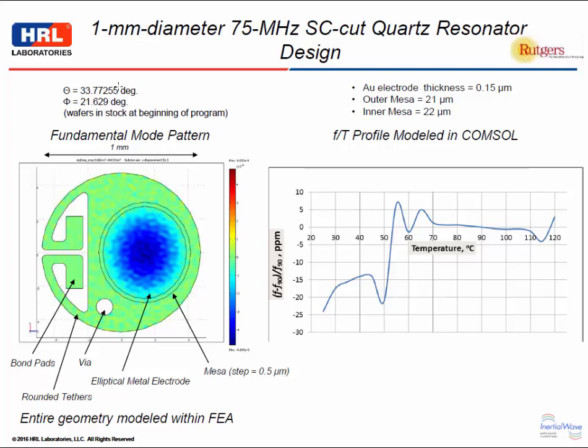We included a MESA step, the inner MESA's 22 microns. There's a half micron step on each side to give us an outer MESA of 21 microns. We used 0.15 microns of gold. You can see that there's some activity out in the regions outside, so we didn't do an exceptionally good job of minimizing activity dips or mode encroachment out into the MESA region, but we only had a month or so to do this design and then get on with the fabrication, so I think we can do better in the future.